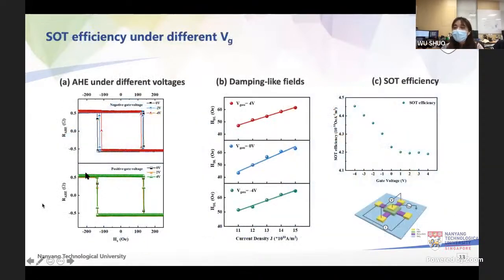And this is the AHE measurement result. You can see when the gate voltage goes from 0 volts to -4 volts, the change in the shape of these loops indicates the modification of the coercivity, but it remains unchanged when a positive gate voltage is applied. We should note that the negative gate voltage creates an electric field from the top layer to the bottom layer. This means oxygen migration from up to down.